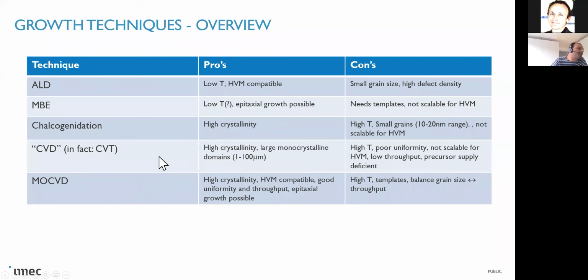And then basically the CVD method, which is in fact a chemical vapor transfer method, which is, I think, the most established in the labs, and which has, let's say, very large monocrystalline domains. But the process conditions are extremely complex to control, and therefore it's very difficult to tune that for high volume manufacturing. And it's also very sensitive to small differences in temperature and in carrier transport.